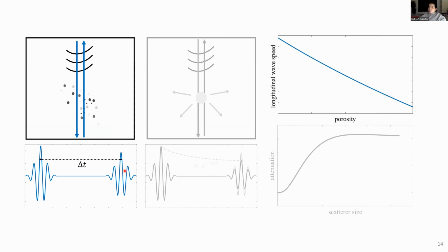So that brings us to some of the ultrasonic results and what we learned from doing this type of analysis. The first thing we did was just look at the wave speed. Again, it's a pretty simple metric we could start with. We were collecting full A scans at every location, and we could do just a cross correlation and get a quantitative measure of the wave speed. Again, thickness independent based on the type of measurements that we were collecting.